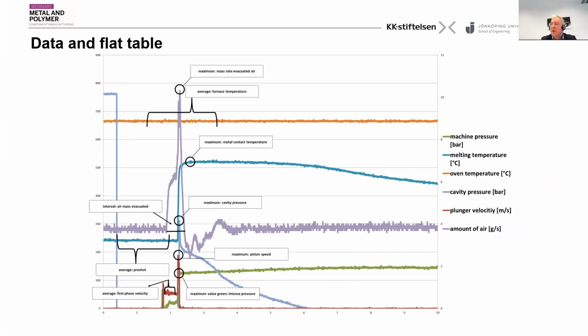In the earlier stages of our analysis we took only maximum data. So we have a curve here and we take the maximum mass rate of evacuated air, or the maximum metal contact temperature, or the maximum cavity pressure here. But maybe it's how the whole curve looks. And this is what we are working on now in the frame of artificial intelligence. We want to analyze the whole curve, because we think the first derivative, how fast the metal contact temperature goes up, also gives you very needed information about the quality of the part. But this is not yet finished. We are still working on it.